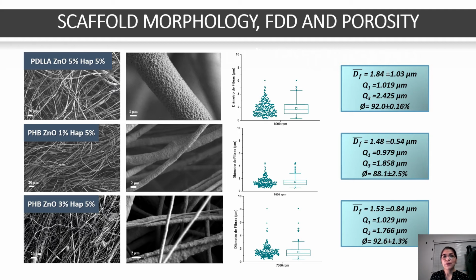As regards PDLLA, fibers were mostly homogeneous with some small defects, probably due to the characteristics of the precursor solution. As already described, the fibers have a rough surface morphology, characteristic of a PDLLA chloroform system. Regarding the fiber diameter dispersion, this was presented in a slightly wider range than that obtained in the optimization phase. It should be noted that these results reflect the variability involved in the preparation of the scaffold, because these are obtained with a collection of fiber for 7 runs, and the optimization of the system was done with the fiber for 1 run.